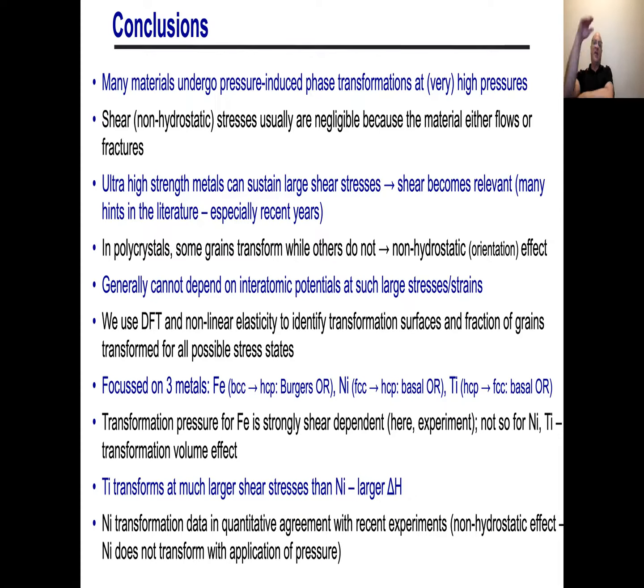Okay, and the part that really originally motivated me to do this work was this very nice set of experiments in nickel done by the Shenyang group. In that case, I'd say our agreement with the experiments is quantitative. I would say we could probably be quantitative for many more materials. There's just not a lot of good data at very high shear stresses.